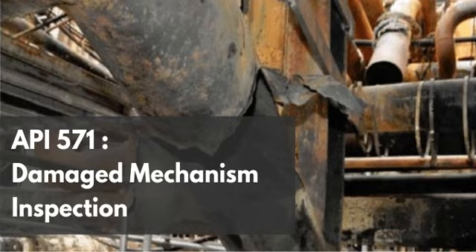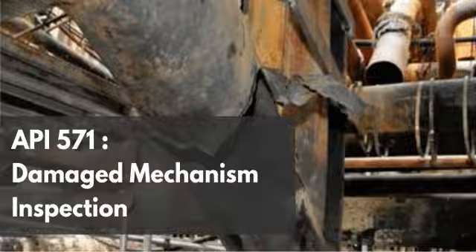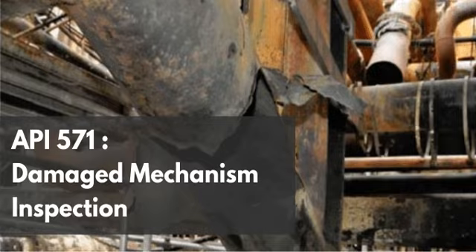Exactly. So when you introduce a specific chemical agent, in this case the amine solution, that agent doesn't even need to do all the work of breaking the atomic bonds, because the mechanical stress has already brought those bonds to the brink of failure. You nailed it. The amine simply acts as the catalyst to push them over the edge. So, as an inspector or an asset integrity engineer, you aren't just scrutinizing the weld cap, you really have to interrogate that invisible borderland a tenth of an inch away. Right. You have to know exactly where to look.